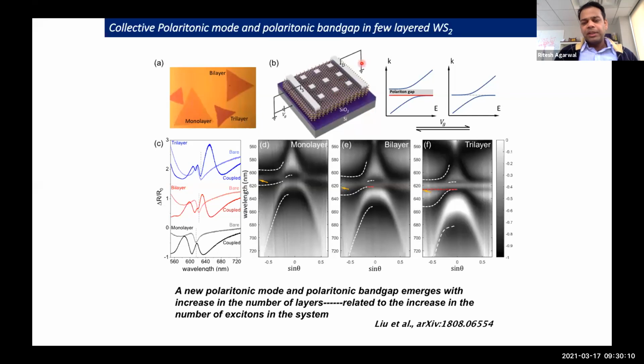If you have this multilayer system, we only tried up to trilayer, and then we pattern this plasmonic lattice. As we go from monolayer to trilayer, a new mode emerged. This dark line, in our reflectance geometry, means there's a resonance there. There's a very strong, almost non-dispersive mode that emerges, followed by this bright region, which means no excitations are allowed in the system. So we call this a polariton gap. And then the upper polariton branch. From here, if we extract the coupling strength, it's of the order of 100 or 110 meV.